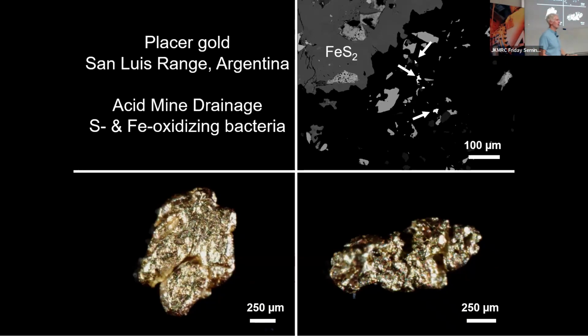It's the geologists that have told the story, gold nuggets grow. It's this idea that they increase in size and will accrete together. So these are samples a colleague gave us to look at. The hypogene material, the black is silicates. We got various mineral sulfides there, and the gold particles are on the order of 10 to 20 microns. If you go 50, 60, 70 kilometers downstream, the gold grains are a couple of hundred microns.